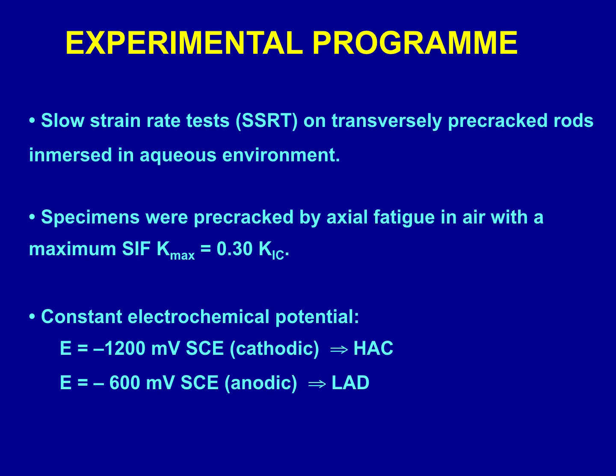The experimental program consisted of constant extension rate tests or slow strain rate tests, SSRT, on transversally pre-cracked rods immersed in aqueous environment. The specimens were pre-cracked by axial fatigue in air with a maximum stress intensity factor, K max, equal to 30% of the critical stress intensity factor, K1C, the fracture toughness of the material. Two constant electrochemical potentials were used: E equal to minus 1200 millivolts versus saturated calomel electrode, SCE, a cathodic potential in the Pourbaix diagram, promoting hydrogen-assisted cracking mechanism, and on the other hand, E equal to minus 600 millivolts SCE, an anodic potential promoting localized anodic dissolution or pure stress corrosion cracking.